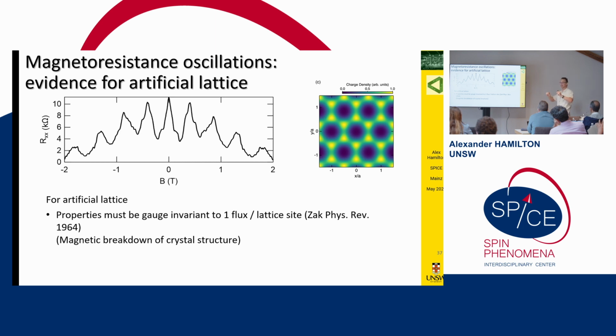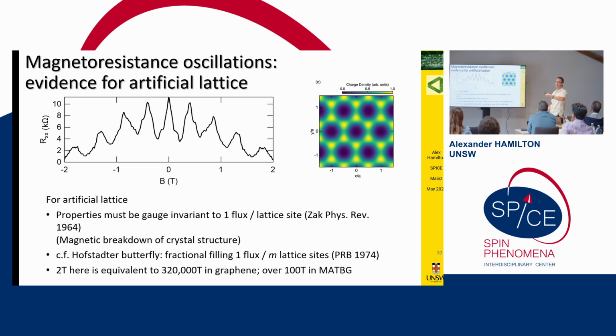If you have a lattice, then if I thread one magnetic flux through that lattice, everything, to quote my predecessor once again, everything should be gauge invariant. So whatever the resistance is, if I thread one magnetic flux quantum through it, I should get the same resistance. So the resistance should be periodic in magnetic flux per unit cell. And this is the magnetoresistance as a function of magnetic field, and you see these periodic oscillations. And this has been known since 1964, and Zak put it down as magnetic breakdown of crystal structure. So this is like the Hofstadter butterfly, but it's the integer version of the Hofstadter butterfly.